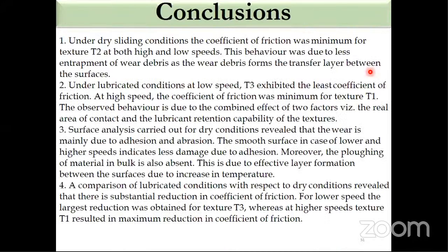So these were some of the conclusions from this study. The coefficient of friction is minimum for T2 under dry conditions, while for lubricated conditions, T3 was the better one. But this was actually observed because of the synergetic effect of two factors: the real area of contact and the lubricant retention capability of the textures. So that was the key observation, I would say.